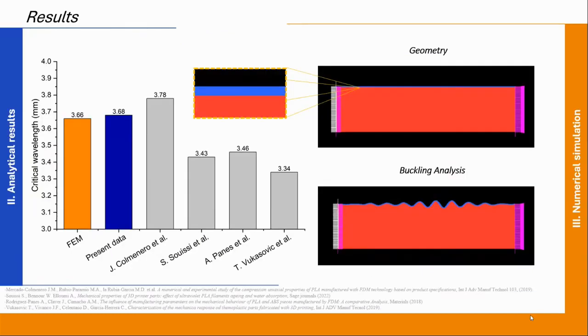The analytical analyses are validated with the numerical analysis. In fact, the two values of critical wavelength are comparable. Moreover, the mechanical properties of the literature are similar to the ones we observed from the compressive test. On the right, we have the results for the buckling analysis.